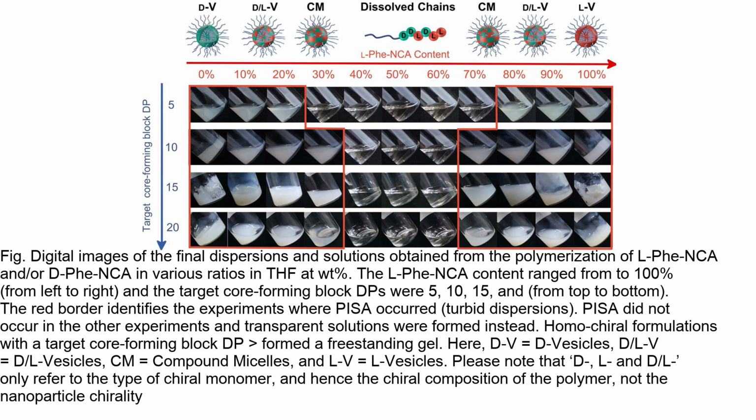Homo-chiral formulations with either L-Phe-NCA or D-Phe-NCA self-assembled into vesicles, as indicated by the red borders in the images. On the other hand, hetero-chiral formulations with equal amounts of L-Phe-NCA and D-Phe-NCA did not self-assemble into nanoparticles and resulted in a polymer solution instead.